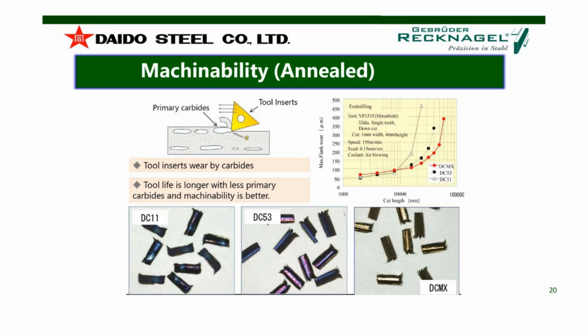And on the right side, the right picture shows the chips during the milling process, and the color is much brighter. And that means we had a lower temperature during the milling process. And the reason is, of course, because of the finer carbides we have. With DC11 grade, higher wear on the tool, and the temperature was going more and more up. The situation with DCMX is completely different. The temperature is on a lower level, and that means the machinability is better, and also the wear on your cutting tool is less.